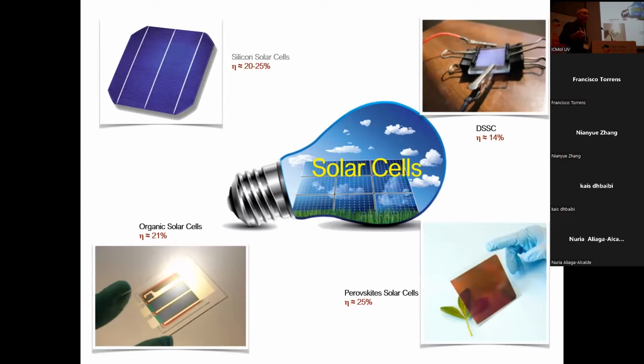The commercially available devices coming from silicon usually are around 16% efficiency, because it's microcrystalline silicon. But for dye-sensitized solar cells or Grätzel cells, this is the maximum efficiency when you are using a solid electrolyte. Organic solar cells jumped very recently from 18 to 21% or so, and the most recent perovskites have been certified at over 25% efficiencies.